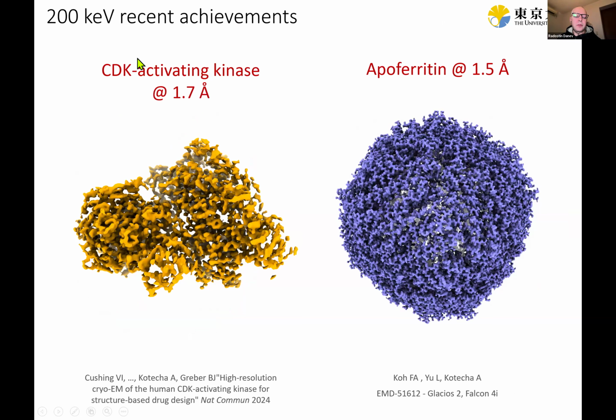Here you see more recent results from the 200 kV machine. So we have here the CDK activating kinase at 1.7 angstrom. This is an amazing result, from a collaboration, I guess, between Abhay Kotecha and Basil Greber. So they did multiple structures, more than, I think, around 15 structures of this protein with different inhibitors. And then by combining the data sets, they were able to get deep sub-2 angstrom resolution of this protein. And the highest resolution 200 kV structure of apoferritin I found on the EMDB is 1.5 angstrom by Abhay and Koh. I guess they haven't published it yet, but this is the highest one that's available on the EMDB.